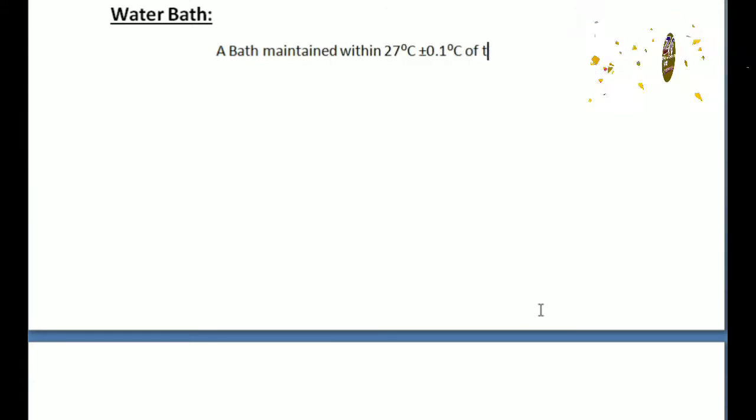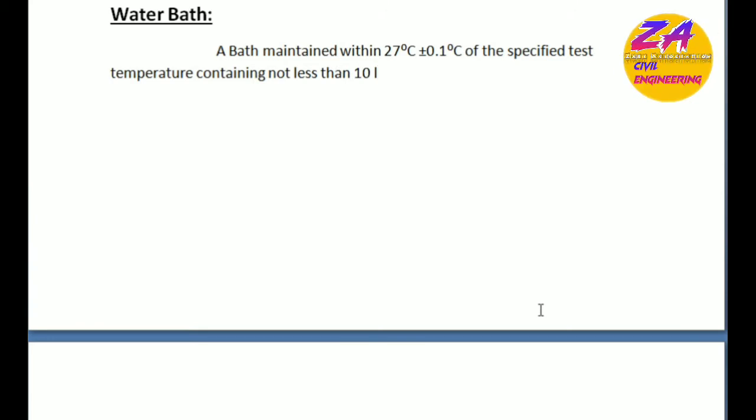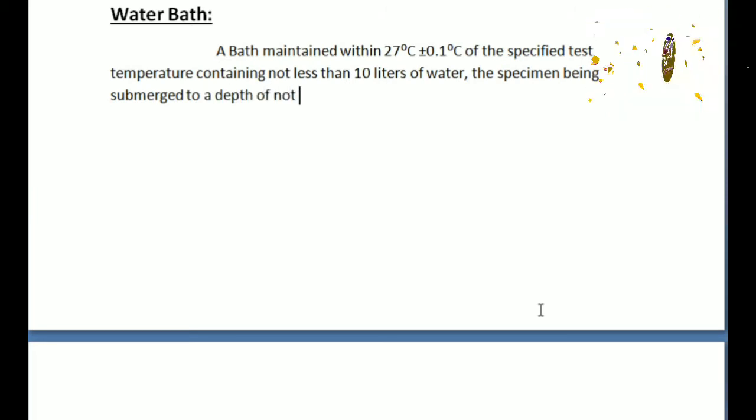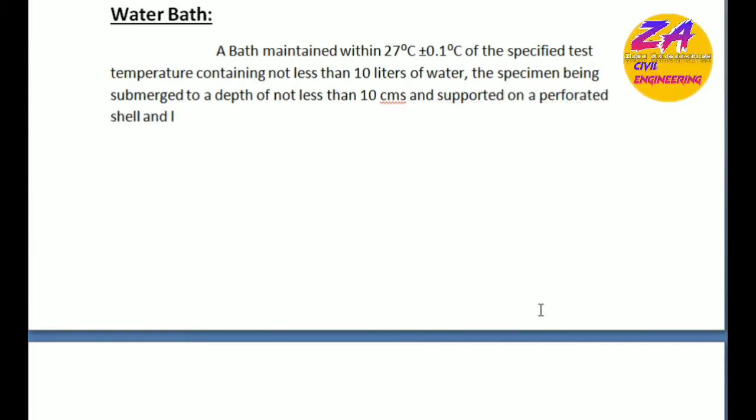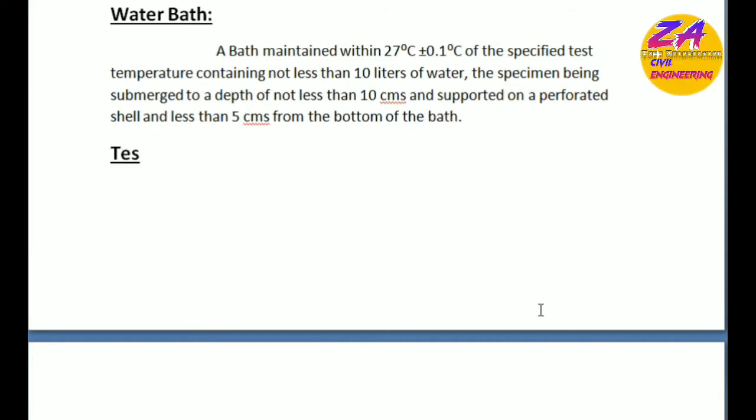After this, the water bath. A water bath maintained within 27°C ± 0.1°C of the specified test temperature, containing not less than 10 liters of water. The specimens remain submerged to a depth of not less than 10 centimeters and are supported on a perforated shelf not less than 5 centimeters from the bottom of the bath.